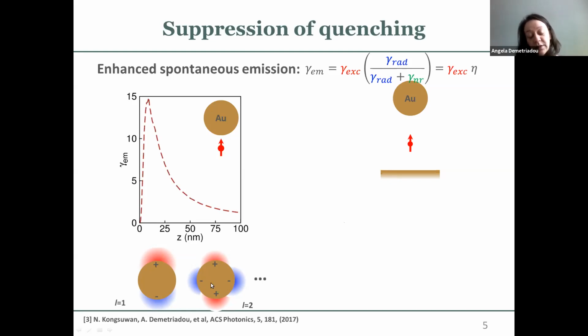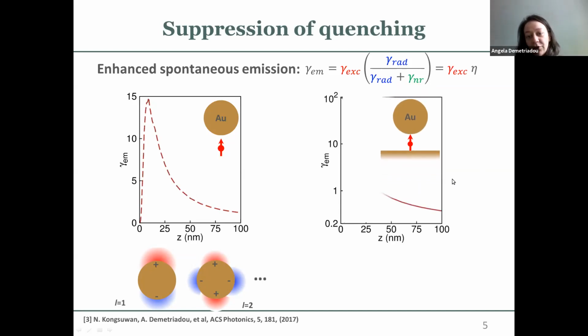And these modes, the second order mode and all the higher order modes, are dark. So as I move closer and closer to the nanoparticle, I channel energy into dark modes, and that's why my emission rate reduces. Now, if I do the same numerical experiment for the system that we call the nanoparticle on mirror system, then what you see is that the emission rate keeps increasing exponentially, and you never really see it reducing. And note here the difference on the scale on the emission rate.